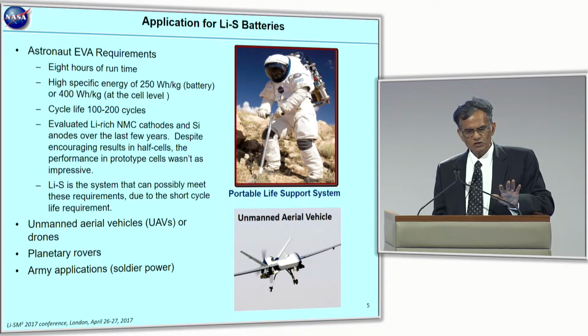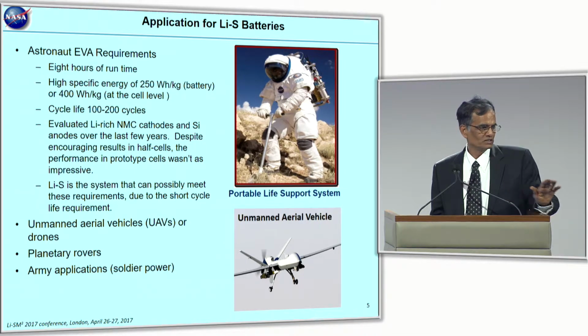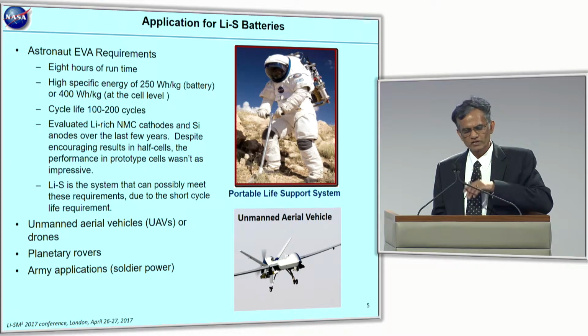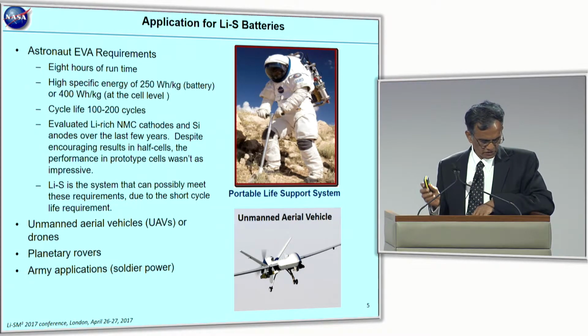next to the lithium ion, we looked at this combination of lithium-rich NMC type cathodes combined with the silicon anodes. We spent quite a bit of time on that, but those challenges are as difficult, I would say, as we see with the lithium sulfur. Right now, the focus is more on the lithium sulfur, with a couple of people working on that. And then another area where this lithium sulfur can probably make some sense would be unmanned aerial vehicles and aircraft. That's something that we are looking at.